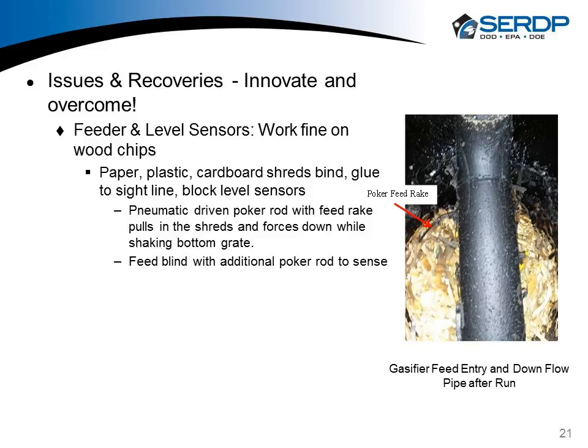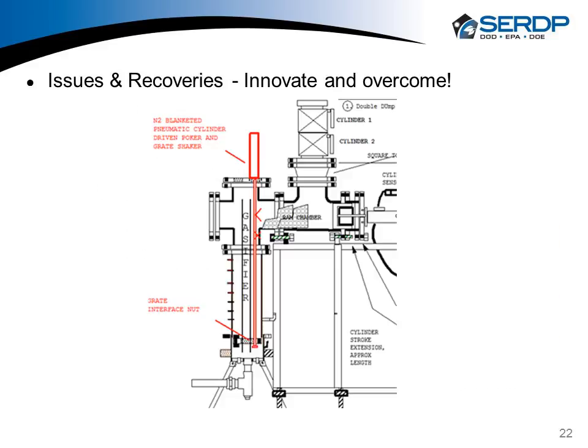And then what also happened is that these things bound up, and we had to add an air-driven rod with these little rakes that would pull this material off of the incoming plug and drag it down into the gasifier, and then they also mixed it up. Here's the diagram of what we put on there. This is the rake that's going to pull the material off as it's pushed forward, and these lower ones tended to mix the material up and move it to the other side of that downflow tube.